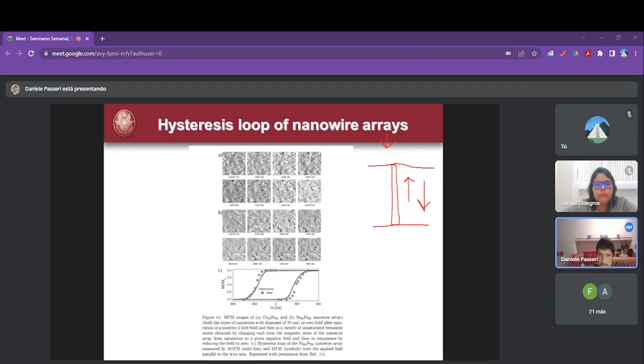And the nice result was that the authors obtained the points here, while the continuous line is the result obtained using a macroscopical system. So this result is very nice because basically you have a link between the behavior of nanometrical sized domains and the macroscopic behavior.